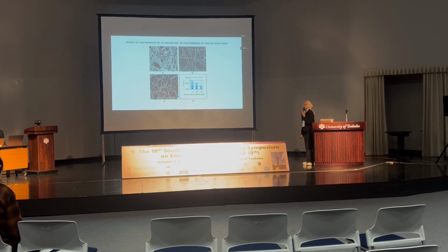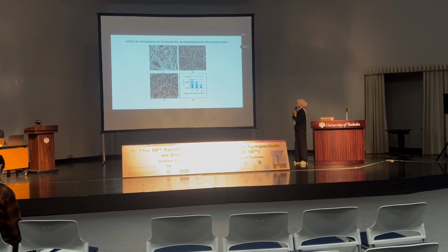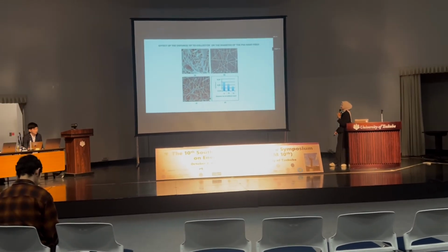Here is the effect of the distance from the tip to the collector on the diameter. It was observed that when the distance of the tip increased from 5 to 10 to 15 centimeters, the diameter of the nanofiber was reduced.